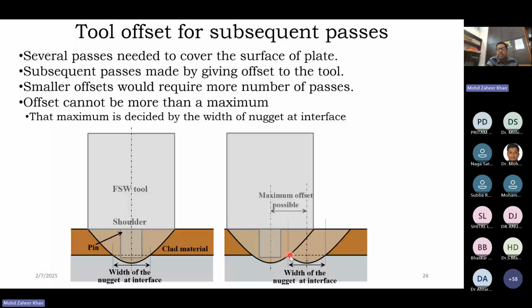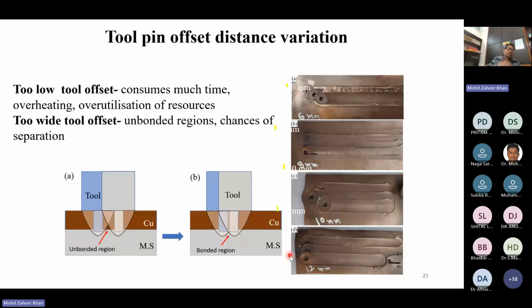Now, why we want to keep the maximum tool offset was that if there is a plate of 10 millimeters and the offset is every time 2.5 millimeters, then it will require at least 4 passes. But if the plate is of the same thickness and we are giving only 1 mm offset, then you have to go for probably 5 or 6 passes. So therefore, to minimize the effort of friction stir processing passes, the maximum possible tool offset is what is desired. And after making this calculation, here also you can see in this pass, if the offset is too much, then there is an unbonded region created over here. And if it is too less, then unnecessarily effort has to be there.